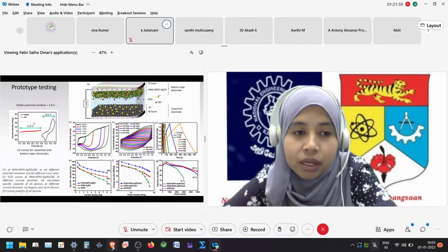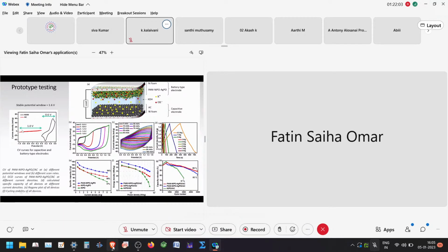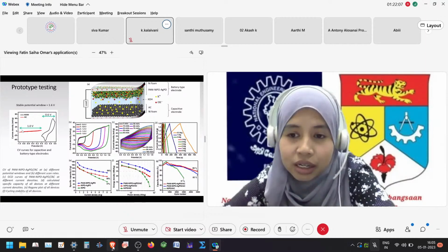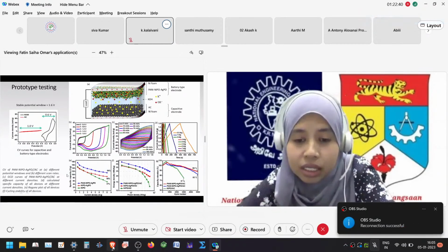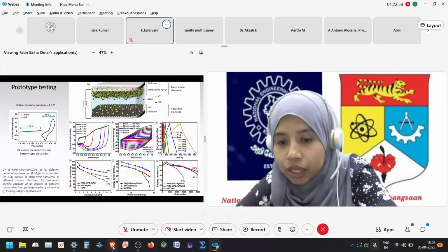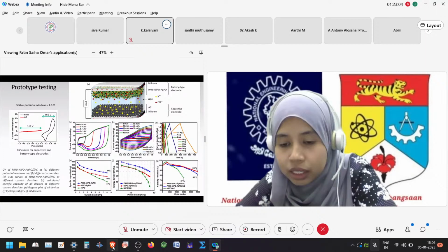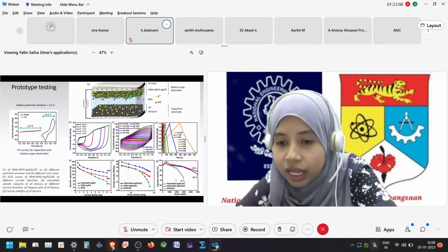And this is the profile of the device when we vary the scan rate from lower to higher, and this is the GCD curve of the device. So this is charging and this is discharging. So again, from GCD we can calculate the specific capacity. We can determine the energy density and power density. Also, this is wrongly labeled. But the device which consists of polyaniline nickel phosphate silver phosphate has better stability as compared to the other electrodes.